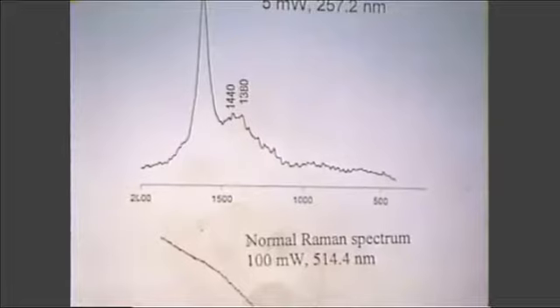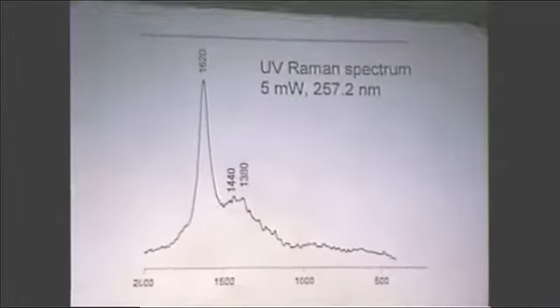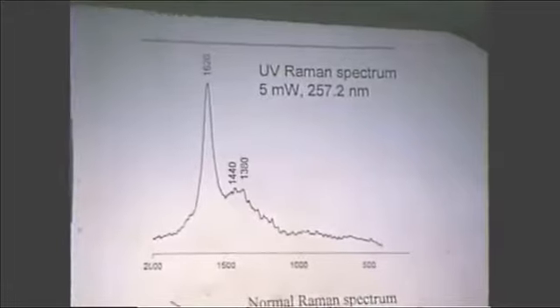One of the catalysts was this rhodium on alumina catalyst that I showed you. So here's the spectrum again, where we just see the broad fluorescence from the sample by excitation in the green. But when we do the excitation in the UV, we get a beautiful Raman spectrum. It's hard for me to explain how pleased and surprised I was that it worked this well. I mean, usually things don't work out so well. It took about 10 minutes to get a Raman spectrum that looks like this. Okay, so we have very nice signal to noise, and these bands here are associated with the coke on the supported catalyst.